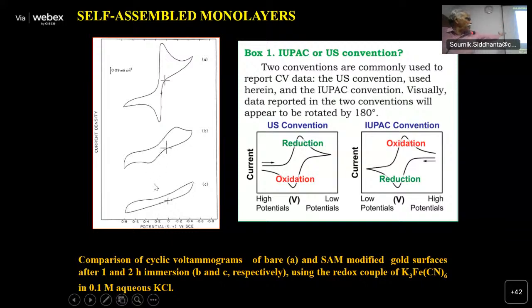So the efficiency of passivation of a surface, whether gold, silver, platinum, it doesn't matter, by a simple monolayer can be investigated by using cyclic voltammetry. Remember, in these cases, you have some pinholes formed. Pinholes will allow potassium ferricyanide, ferrocyanide ions to diffuse. That's why you are getting a little bit of activity. So the evolution of the monolayer formation, initially multilayer, monolayer, all that can be investigated by using external redox probes, such as potassium ferricyanide or ruthenium hexammine. The quality of the monolayer can be investigated by using voltammetry.